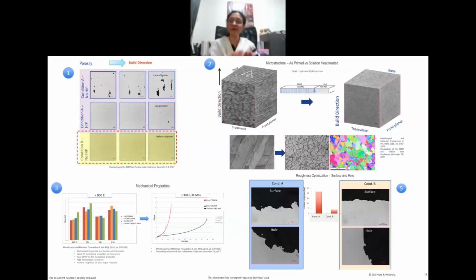But you need to watch out not only at room temperature if the application is at high temperature. So we straight away went out and, of course, we developed all the room temperature strengths. That is a no-brainer. That has to be done as a statutory thing. But we straight away went and compared the high temperature mechanical strength. In terms of the baseline, a lot of people ask, do you have a baseline? Is ASTM having a standard for additive manufacturing? Remember, you don't need to have the standard, because when we are trying to develop a new part or a new product or a new alloy for additive manufacturing, we do have a baseline in what we are comparing it with, the equivalent cast or wrought part. And that is what we did in the slide.